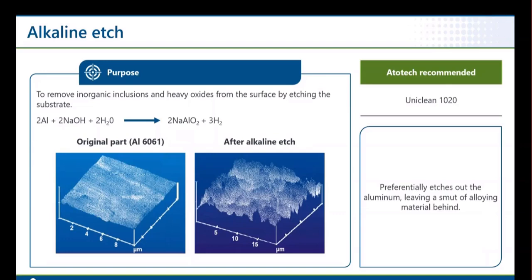the aluminium surface can have quite a lot of cavities develop under the cast skin. The cast skin usually is about 200 microns in thickness, so we have to take special care that we don't break this skin and expose the cavities underneath, because any cavities we generate then will show up as either pits in the surface or will retain some of the chemical residues from the previous steps, and this can lead to corrosion and adhesion failures. Next slide.